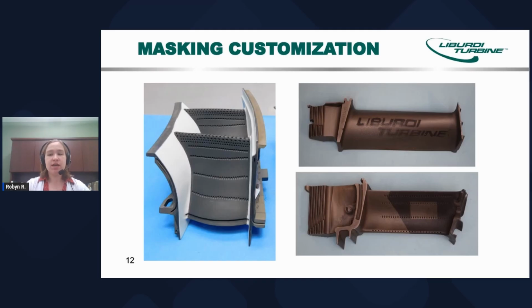on the left. This part requires the oxidation and hot corrosion resistance on the airfoils provided by the aluminide coating, while the shrouds need the temperature protection of a TBC coating. With the LSR slurry process, we can set up these two different coating methods in a streamlined way to not interfere with one another and to get the best optimization of the part.